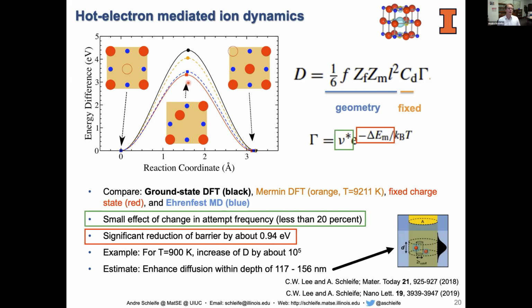So in other words, this electronic excitation can increase the diffusivity. We can play some number games by making assumptions here for the temperature and, we know the geometry of the material. And so just to give you one example, at 900 Kelvin in this material, diffusivity increases by about 10 to the power of 5. That depends, of course, on the proton flux and things like that. So we give in the paper some examples, but the point being here, this excited electron effect can increase diffusivity.